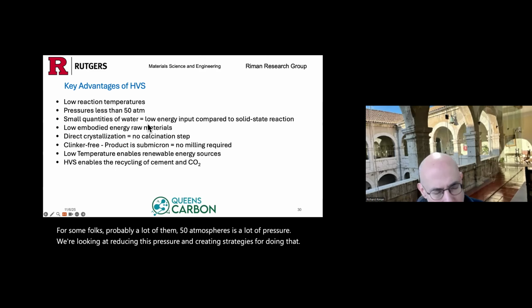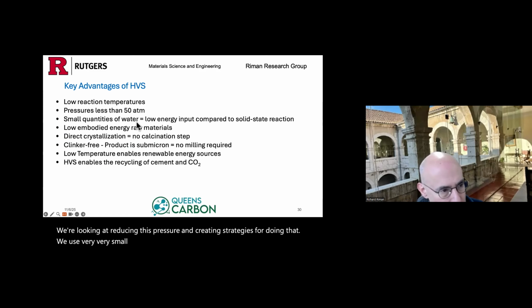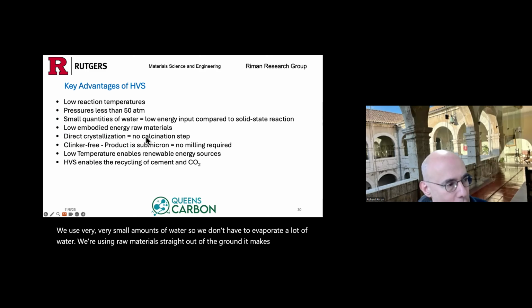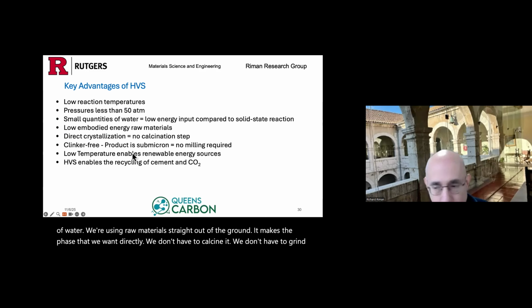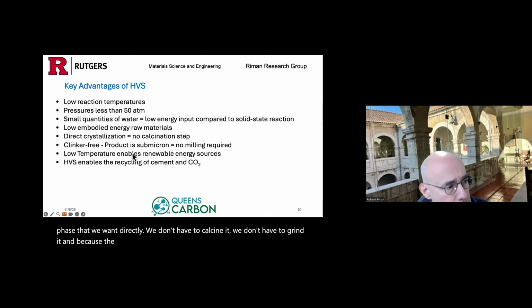We use very, very small amounts of water, so we don't have to evaporate a lot of water. We're using raw materials straight out of the ground. It makes the phase that we want directly. We don't have to calcine it. We don't have to grind it. And because the temperature is below 400 degrees, we can use renewable energy like phase change salts to power the process instead of using fossil fuels.